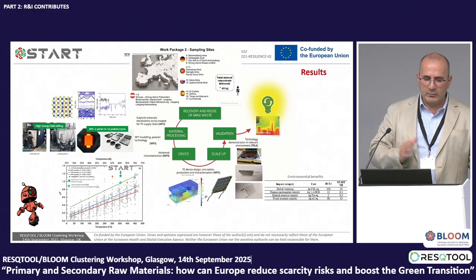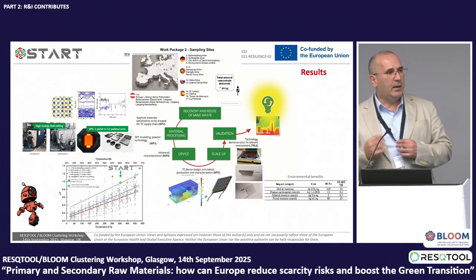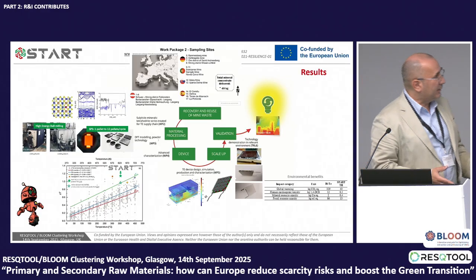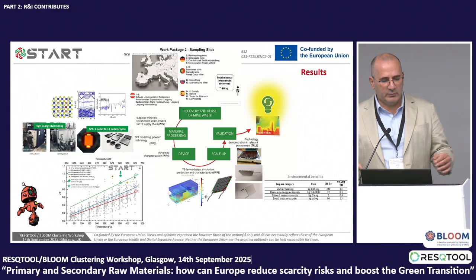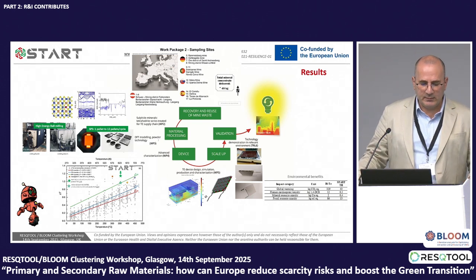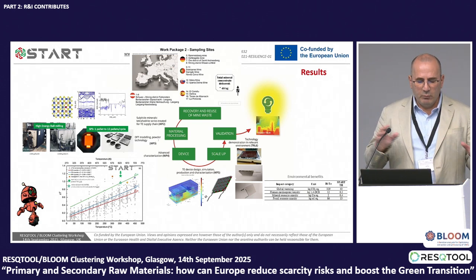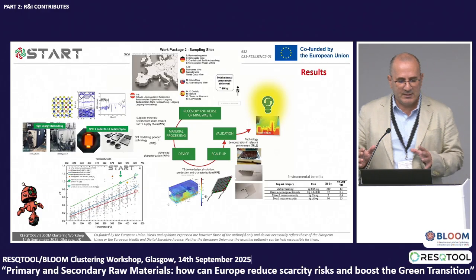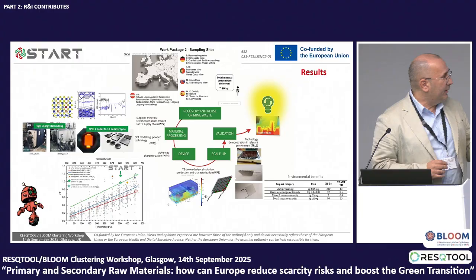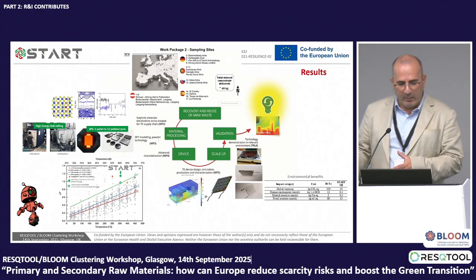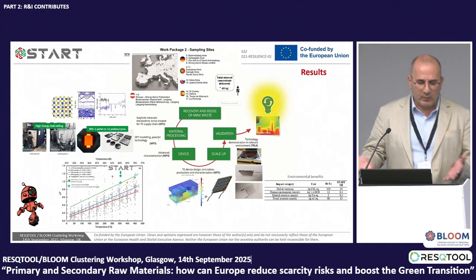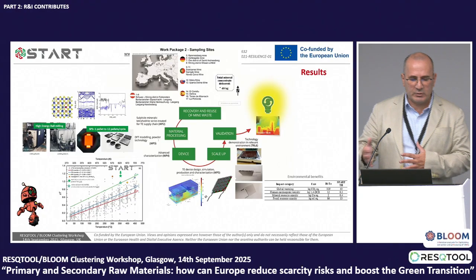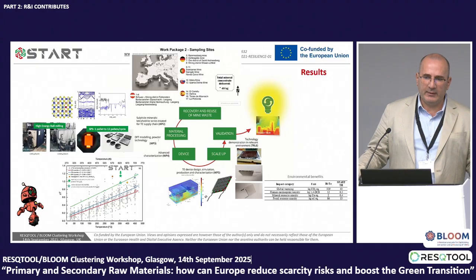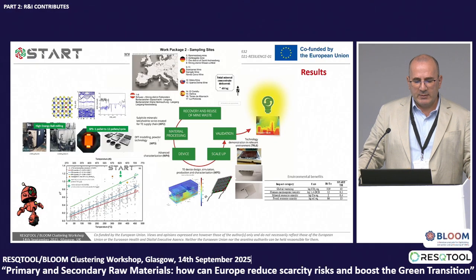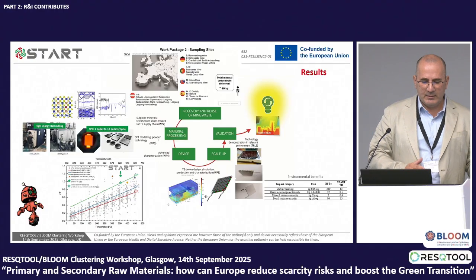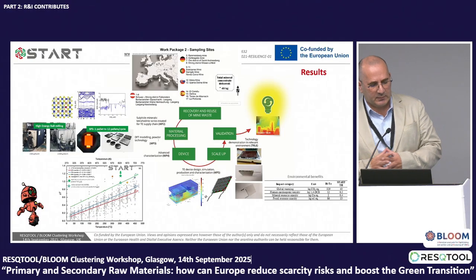We have used those processes that are there indicated, high energy ball milling followed by spark plasma sintering. I'm not going into details about these two technologies. But we were able to upscale these processes. For the high energy ball milling process, for example, we are at a pilot scale, which means that we are able to produce around 1 kilogram per batch per cycle. For the SPS consolidation process, we moved from 1 pellet per cycle to 12 pellets per cycle.